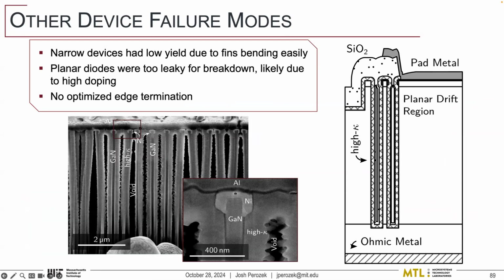And the other thing is that there was no edge termination used for these devices, which is very strange, but the fin diode has intrinsic mesa isolation in that the edges are always etched all the way down through the drift region. So it does ease a lot of the edge termination that you would typically need for these type of diodes.